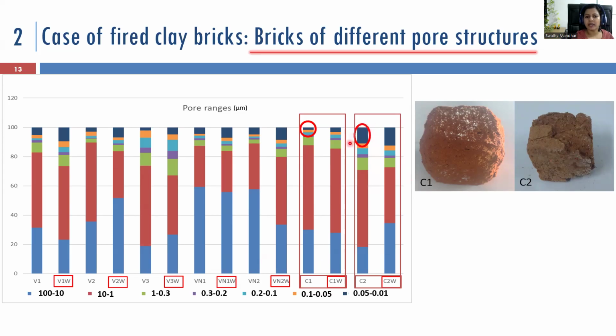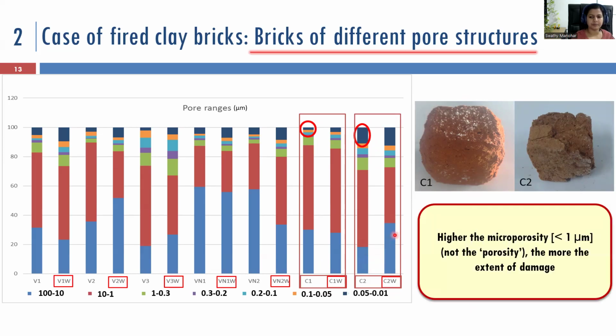In C2, if you look at the microporosity, it was close to almost more than 15%. But C1 had much smaller microporosity. We already know that salt crystallization will happen only in these micropores, which are damaging. This material has a large amount of microporosity, which resulted in damage, and you can see here how many more cracks and fissures are being formed in the material. That's why the macroporosity is increasing.